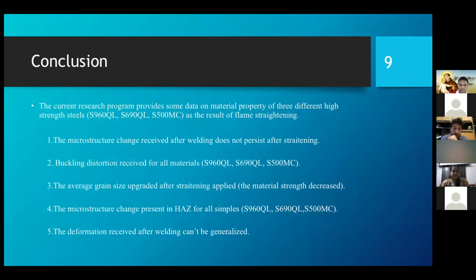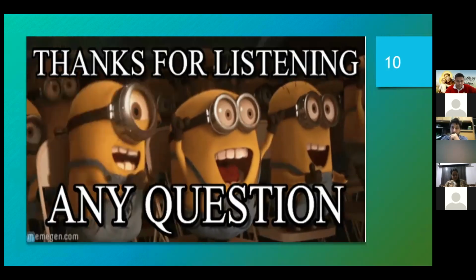So as a small conclusion for this experiment, we can conclude that the microstructure change for all those types of materials does not persist after the straightening, and the same deformation was received for all of the materials using GMAW welding. Also, the average grain size increased for all of them. That means the strength of our material decreased in all those types of materials, and the microstructure changes were received only in the heat affected zone. And also the deformation after welding cannot be predicted, so different deformation was received for all of the materials. So I think this is all for my presentation, and if you have any questions, I'm here to answer.